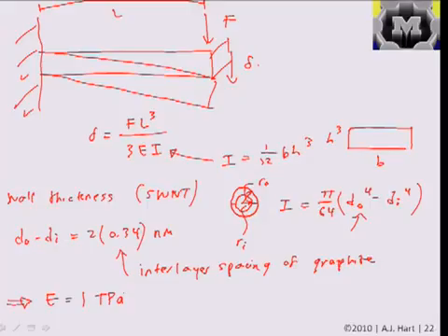As a convention, I like to think that if we say we have a 1 nanometer diameter nanotube, that to me corresponds to the middle space between there. So if you asked where the nuclei of the atoms are, we're going to say they're right in the center here, and the inner diameter is the diameter that we're quoting minus 0.34, and the outer diameter is that diameter plus 0.34. And this becomes more important if we think about multi-wall nanotubes, so nanotubes that have multiple shells.